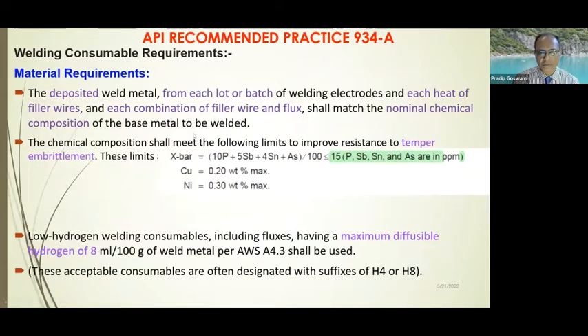In order to fulfill all these, we need to have many things under control. The most important thing is the welding consumable. Welding consumables typically have a factor called X-bar, which is a very well-known factor to all the fabricators and welding consumable manufacturers. The X-bar should not be more than 15. This empirical value is calculated from the tramp elements, whose values are in ppm, with the total summation divided by 100, and it should not be more than 15.